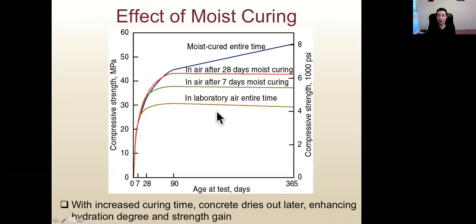So all four concretes, these four lines, have the same mix design - same amount of water, same amount of cement, sand, and aggregate. The only difference between these four concrete is the length of curing. The yellow line is the concrete in the lab, air entire time, so no moisture curing at all. The green line is in the air after 7 days of moisture curing.